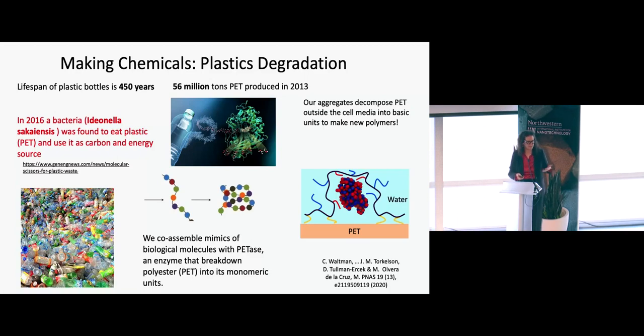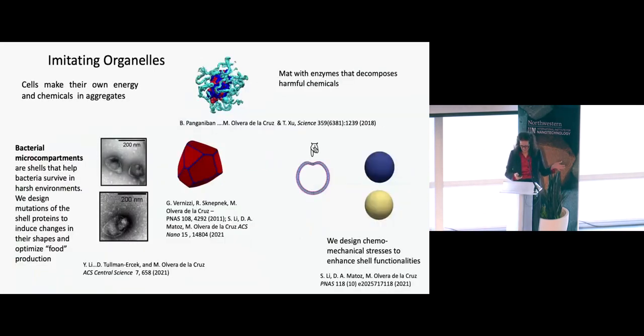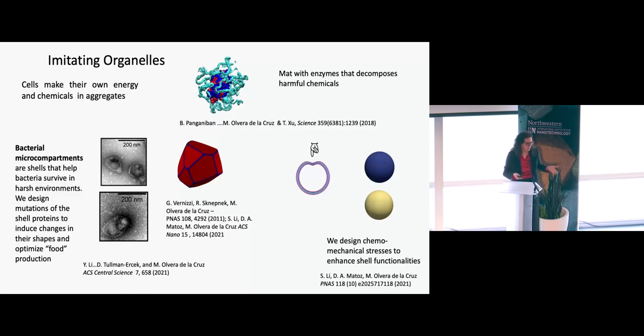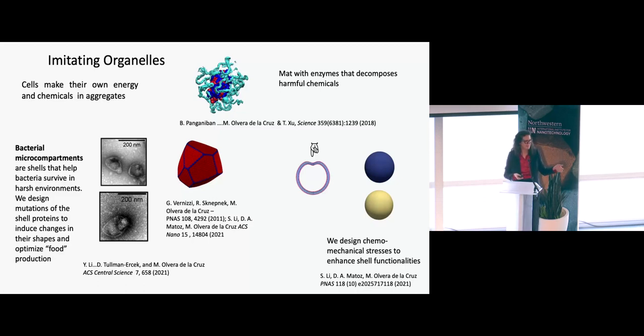This is a nice example of collaboration. There are other ways we use biology to make chemicals—for example, imitating organelles. In some organelles, cells make their own energy and chemicals in aggregates very similar to an enzyme covered by a polymer, but with biomolecules. We have been able to cover other enzymes with designed polymers. You can dry the water, and because the polymer likes organic solvents, you can polymerize and make a mat—a piece of material that is enzymatically active. We made one that degrades OPH, organophosphates, which are materials used in chemical weapons.